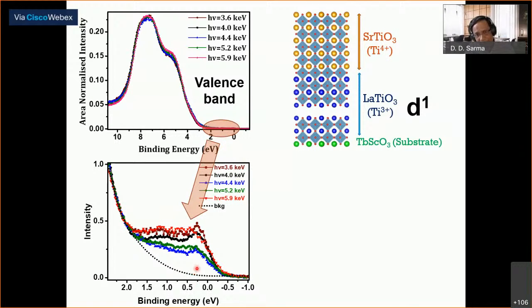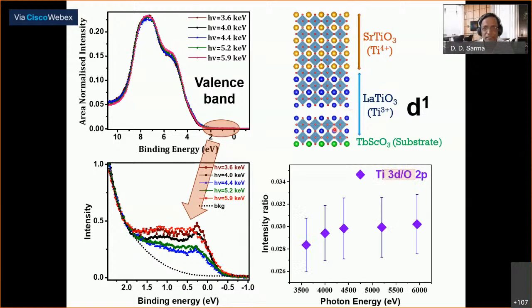And you can see that there's a systematic change with the photon energy change that tells me that the electronic structure itself is evolving as I look deeper inside. And by analyzing this data, I'll be able to tell not only how the electron that is mobile, that D1, is distributed along the depth, but I'll also be able to tell its character in terms of how correlated it is by looking at its incoherent part, the Mott-Hubbard sideband. And this is what we do.